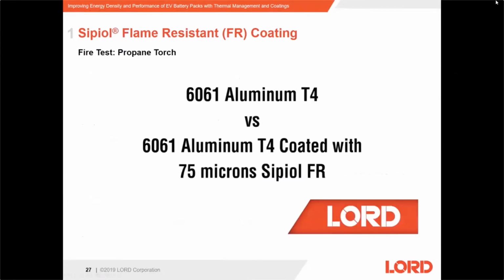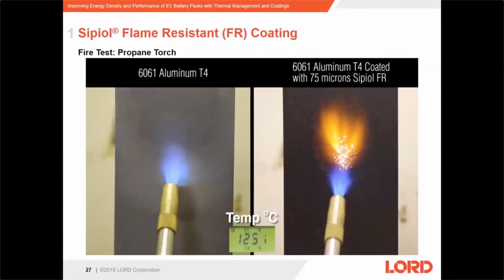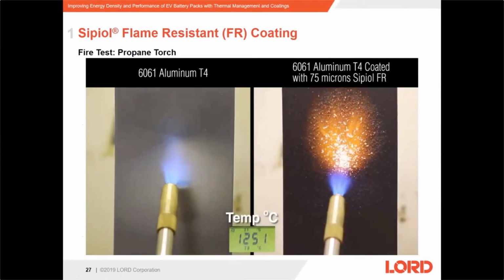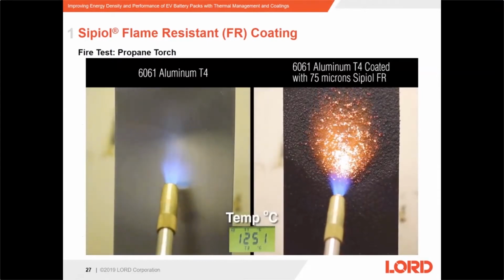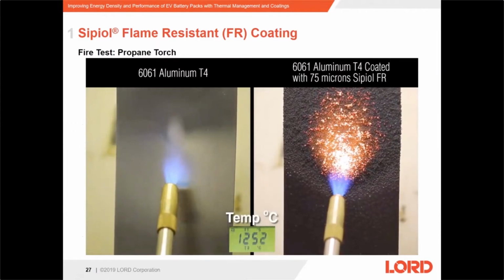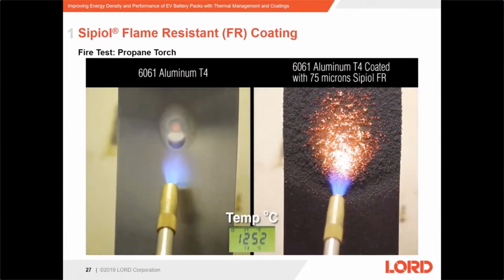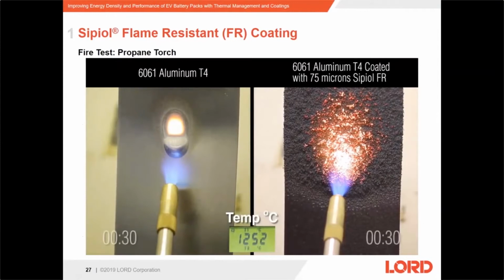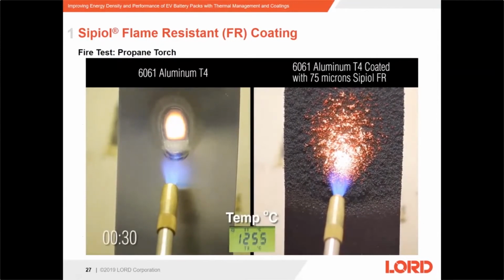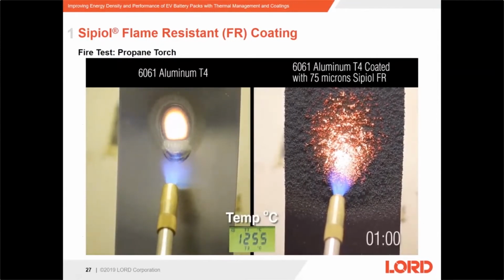Here we have a video of the performance of bare aluminum compared to Sipiol FR coated aluminum when exposed to a flame that is over 1200 degrees Celsius. As you can see, the aluminum is already beginning to be affected, and within 1 minute, it will actually start to melt.